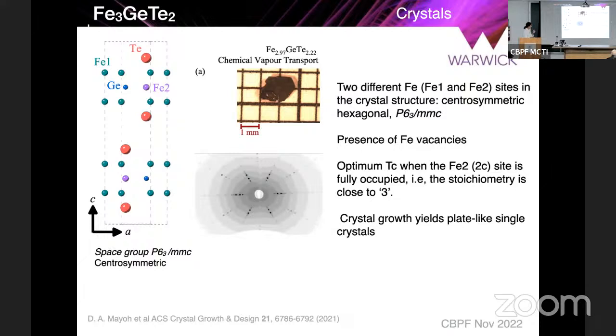So you need to have this iron 2 site, which is the 2c site in the Wyckoff position, fully occupied to give you a stoichiometry of Fe3 in these materials. And only if you hit that Fe3 stoichiometry can you get the highest TC, okay? So how do you achieve that? Now you can grow single crystals again by the chemical vapor transport that I spoke to you about earlier, where you use a transport agent and you get these crystals.